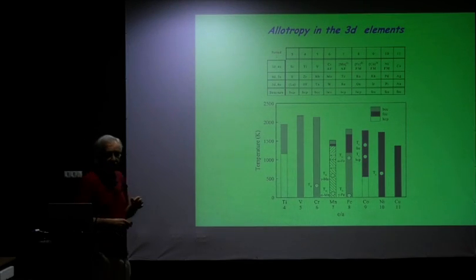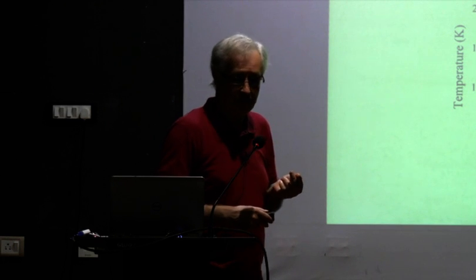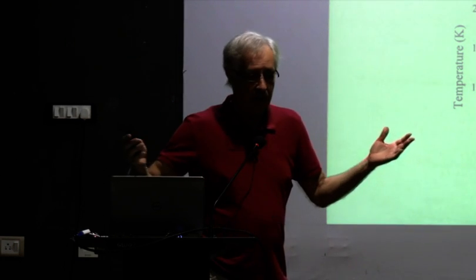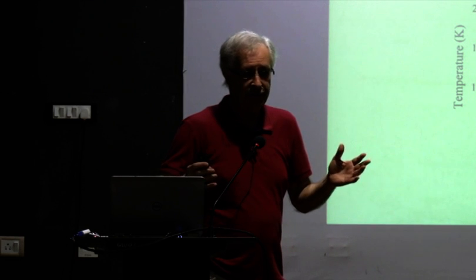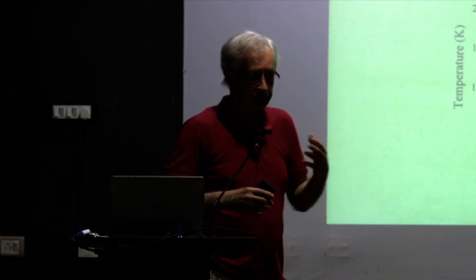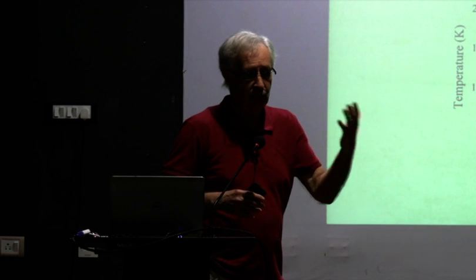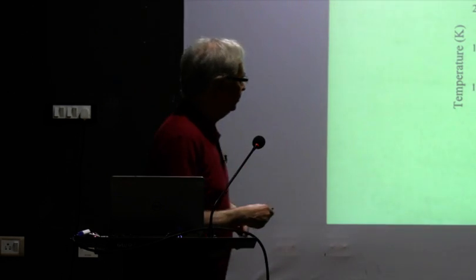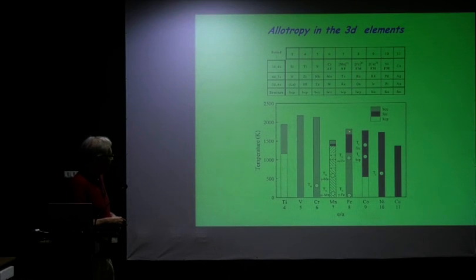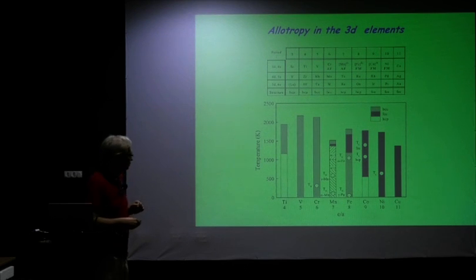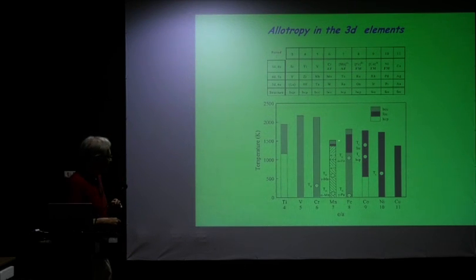When you go to higher temperatures, the BCC state recovers again. It's because it's a more open structure than the FCC, and it is expected that you would go into a more open structure at high temperatures. So what is actually happening is that you see this BCC region opening up and then narrowing down, and after this there is no body-centered cubic structure. After this, as of manganese, you see the face-centered cubic region opening.